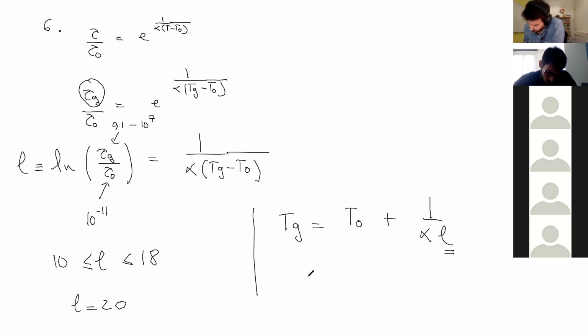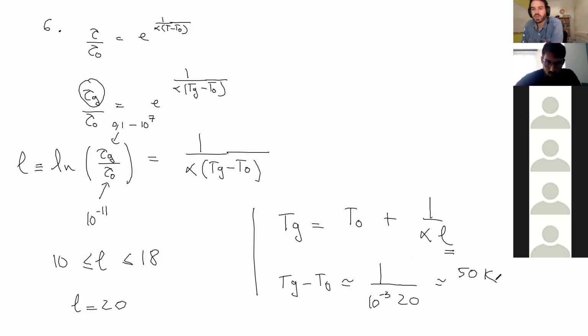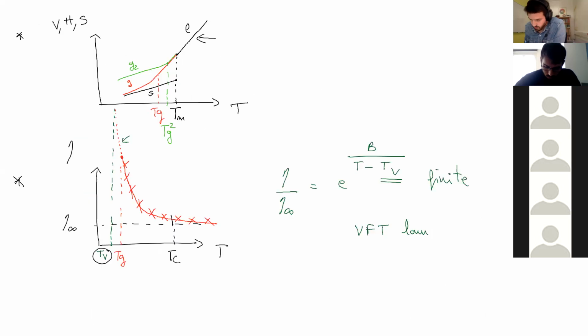And if we put orders of magnitude, Tg minus T0 is equal to 1 over alpha, which is 10 to the minus 3, times L, and we said it's 20. So typically, if I put a 5 here, it's 50. So Tg minus T0 is 50 K, which is very reasonable. Remember here,